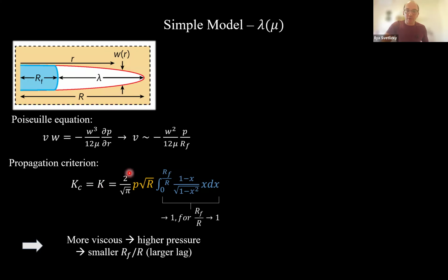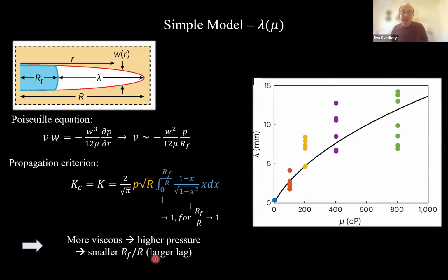And the argument is the following. For some reason, as I indicated, the fluid flows pretty much at the same rate, regardless of the viscosity, something between 3 to 10 meters per second. So if you take V to be constant, what this equation means is that the higher the viscosity is, the higher pressure you need to drive the fluid, which sounds trivial. Now, if the viscosity is higher and you need larger pressure, this part increases. But in order to keep the K constant, the integral should decrease. And the only way for the integral to decrease is to increase the lag. So the more viscous, the higher pressure you need to apply. Higher pressure you have, the larger the lag you should get. So you plug the numbers, and I think you get a good result relative to the simplicity of the model.